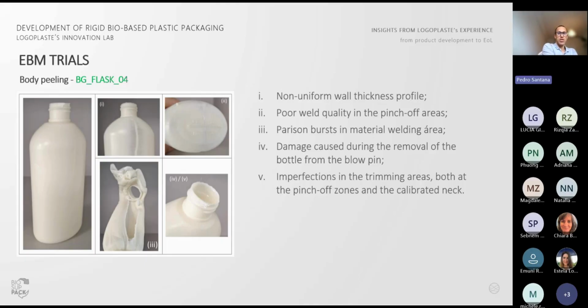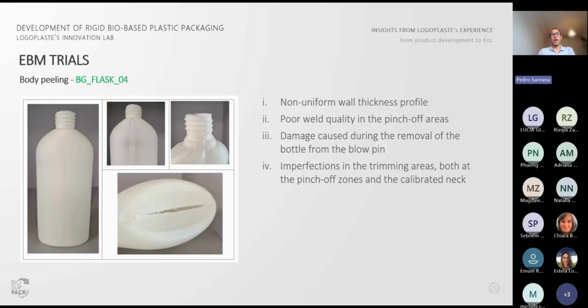During the melting and extruding stages, insufficient material adhesion was also observed, making it difficult to achieve a stable parison formation. Finally, damage occurred in the area where the blowing pin was removed after blow molding, leading to imperfections around the neck area and compromising both the aesthetic quality and the functional performance of the packaging.